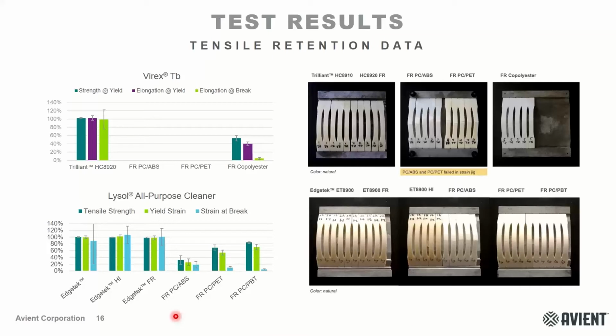And so when you look at the tensile data, that can also help you interpret what sort of damage has been done to the material. Again, targeting 100% retention, which you see for the Edgetek series, the base grade, the high impact, and the FR. And then for the FR PCABS, a very significant loss in properties here, PCPET as well. And the PCPBT showed a significant loss in elongation at break, as well as some of the yield strength of the material.